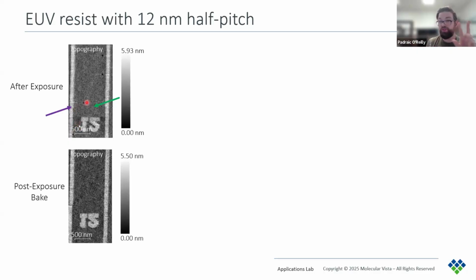With these more zoomed out images, it's easy to see the unexposed regions since they are taller, so these lighter colored lines and this number here. So we simply move the tip to one of these raised regions and take a spectrum that will show us the unexposed area, or the unexposed spectrum. And then similarly, we move to a lower region and take a spectrum on the exposed regions. We're going to refer to the wave numbers used for imaging as wave numbers A and B.